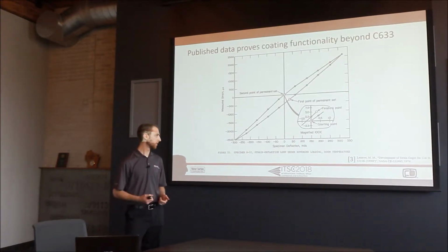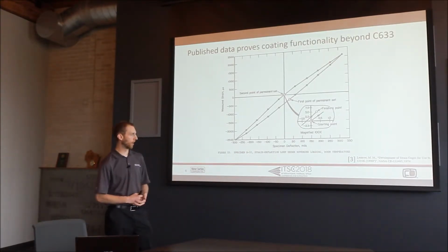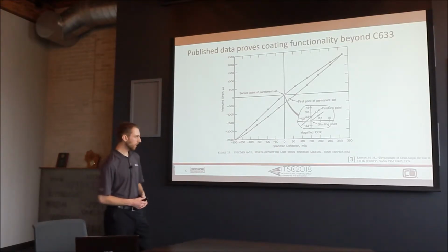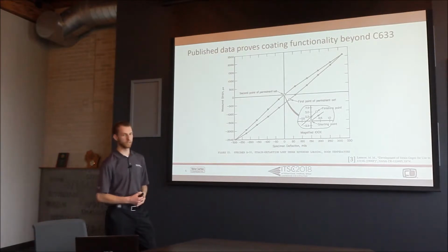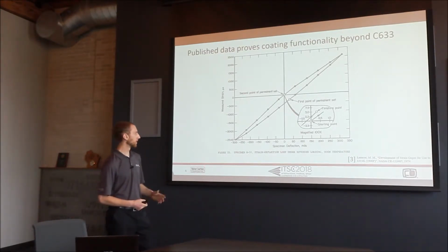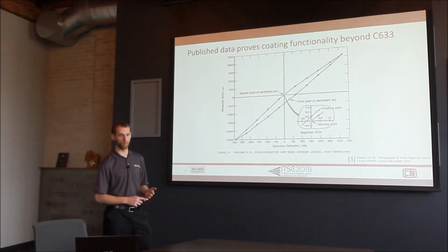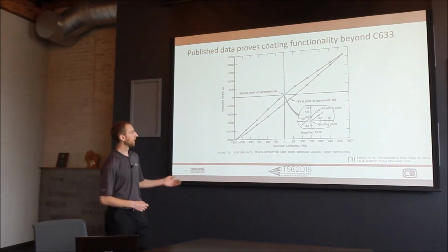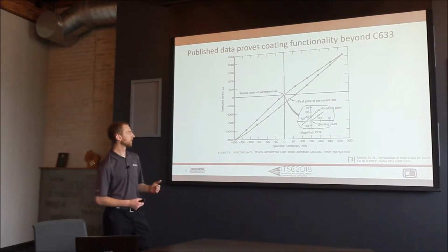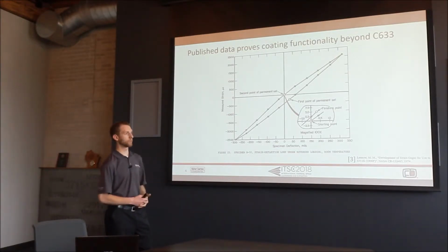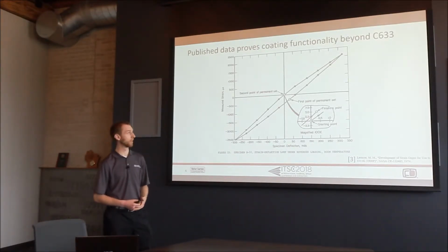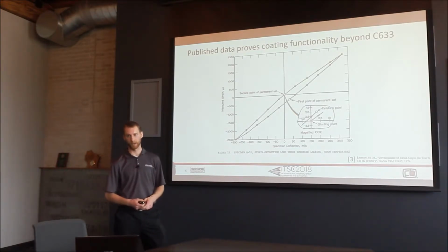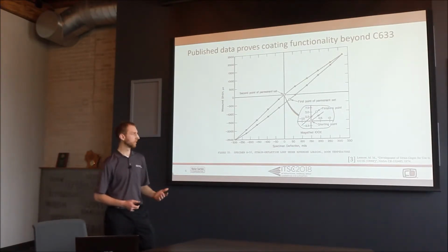This is one example of data that was previously published by Lemko and also Daryl Cromer at Battelle. This is through a constant radius cantilever beam test. It's a fairly complex aluminum, nickel chrome, multi-layer coating applied to Haynes 25. With loading up to 2,000 microstrain right at the coating interface, because of the Haynes 25 alloy, we are seeing that the adhesion strength is well beyond the C633 limits, as 2,000 microstrain correlates to about 65,000 psi. So that's one example there.